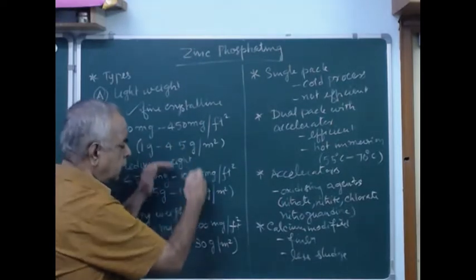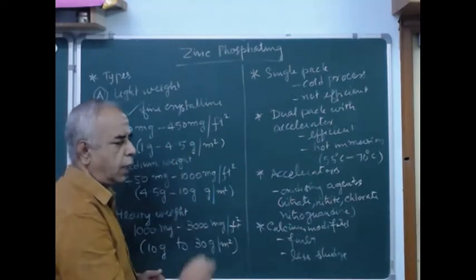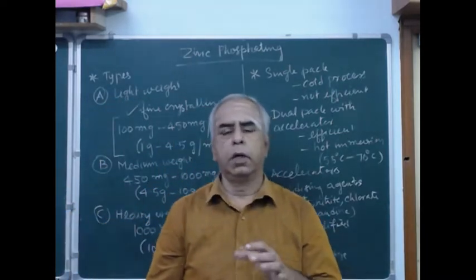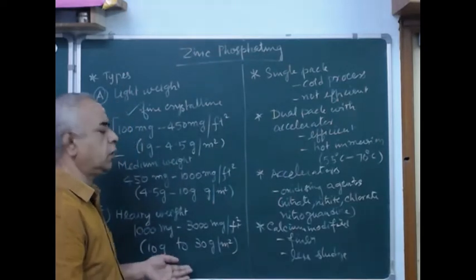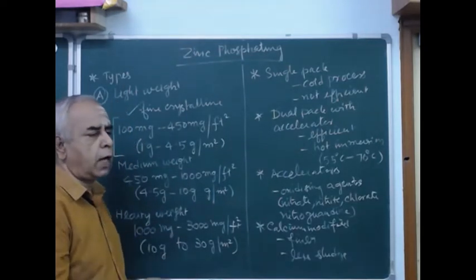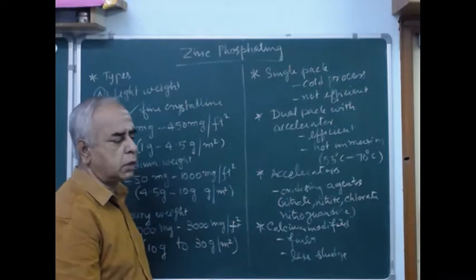With the increase of coating weight, you can have better corrosion resistance. But it will sometimes complicate also. Heavier the coating, it will have hygroscopic tendency.